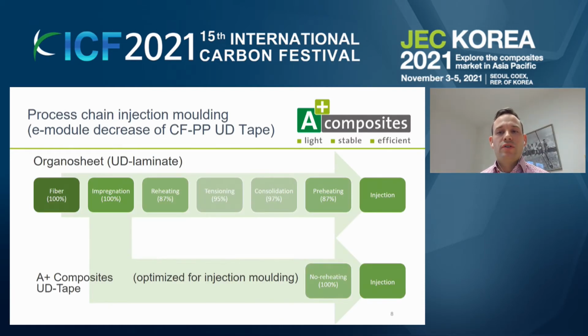So if we now recalculate the Young's modulus, which was about 120, and compare with the actual datasheet values, we can maintain 100% of the Young's modulus in the tape. So this is after the impregnation step. If we now reheat the material, we lose about 13% of Young's modulus, which is quite a lot, because the fibers will go in different directions. And even if we keep in mind that the thickness increase of the deconsolidation is post-calculated, we cannot achieve the original value. If we do now a tensioning, which I show you later on for the tensile forces, we can even increase the values up to 95%. And if we consolidate it again, we have about 97%, which is quite a lot.